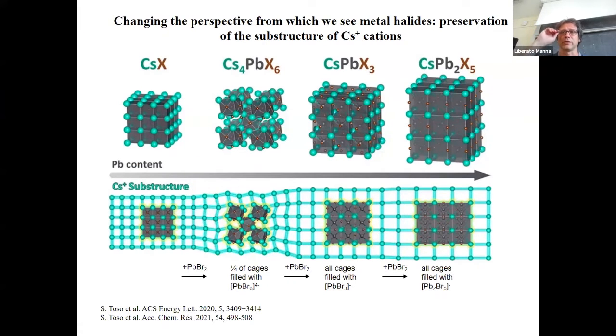Now, the way we can put together all these reactions, and this is actually the topic of two papers, of which one is an account, is to imagine all these nanocrystals not from the point of view of the network of lead halide octahedra or polyhedra, but simply from a cage of cesium ions, which have at their interior either halide ions, as in the case of cesium halide, let's say cesium bromide, and then all the way to cesium lead 2 bromide 5, for example. When you go through all these transformations, what you're doing is inserting neutral lead bromide into the cages, and the bromide initially present in the cages also reorganizes.